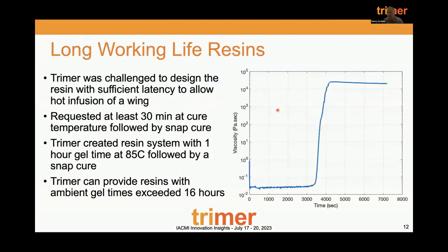We have also demonstrated we can make very long working life resins. So it doesn't have to be these fast components. If you're looking more at large-scale aerospace infrastructure-like parts, we can dial in that cure to be extremely latent. In this case, this was something of interest for HiCam, a program to look at infusion of large-scale aerospace parts. The challenge posed to us was, can you manufacture a part with heated tooling at say 80 or 85 degrees C, allow it to infuse over an hour, and then snap cure following that?